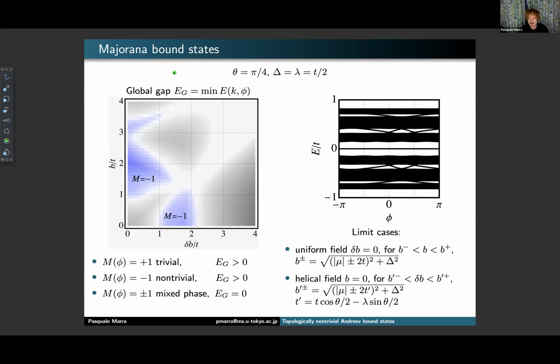Here I show the numerical results of this work. Here I plot the global gap of the system, which is the minimum of the particle-hole gap, as a function of different choices of the phase. For example, this is the spectrum of the energy bands of the system with a Majorana bound state here. Here on the two axes are the applied magnetic field and the intensity of the helical spin field.